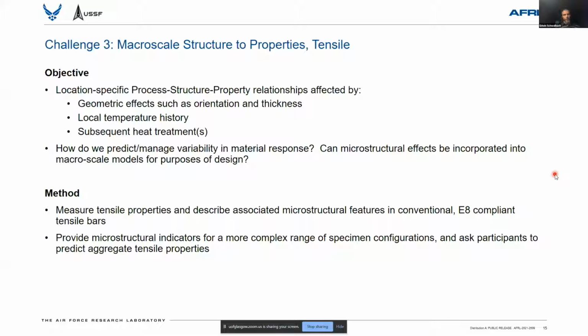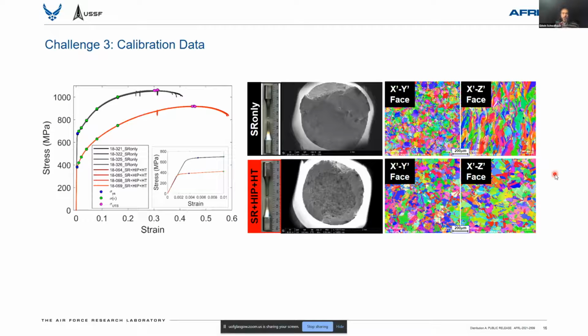So again, we've heard a few times about the effect of location specific variations in the process that can change microstructural features. Looking at things like the thickness of a component, its orientation, and then things outside of the build, things like subsequent machining operations or heat treatments that can modify the microstructure. So here, the calibration data consisted of printed tensile bars. We basically provided the tensile behavior. So you see the stress strain curves for ASTM E8 compliant round machined tensile bars that came from an additive manufacturing build.